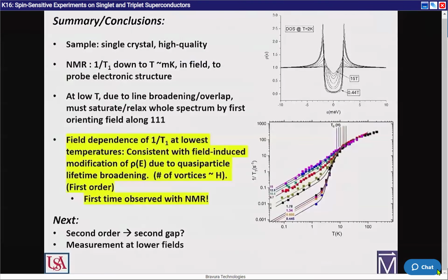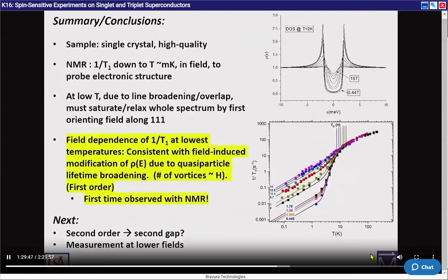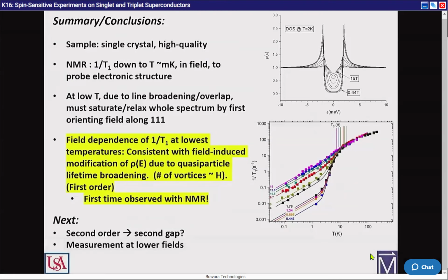So in conclusion, we have studied the field dependence of the relaxation rate well into the lowest temperatures, and have found that the density of states itself is being smeared out by quasi-particle lifetime broadening. So yeah, the vortices are messing with the gap, with the density of states, and this is the first time, it's not the first time it was observed, but it's the first time observed using NMR. And that's pretty exciting stuff. Thank you very much.